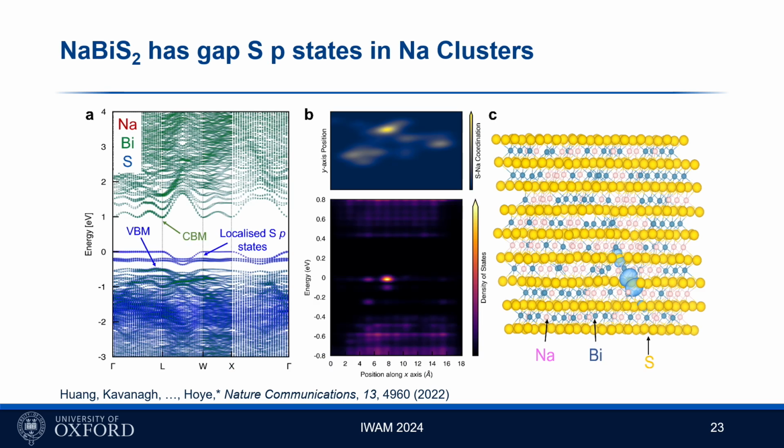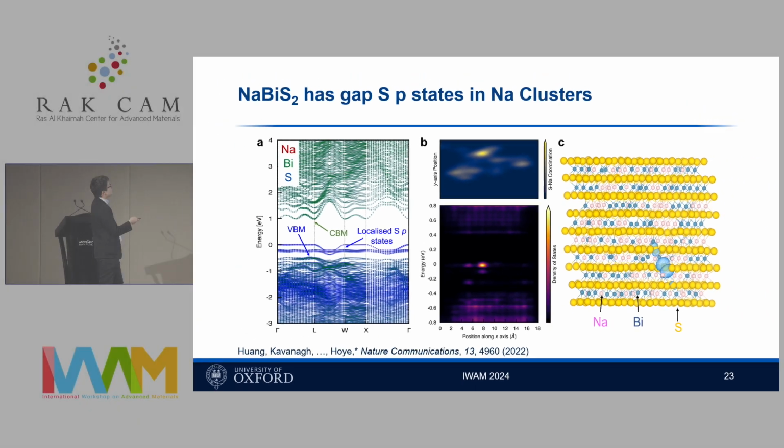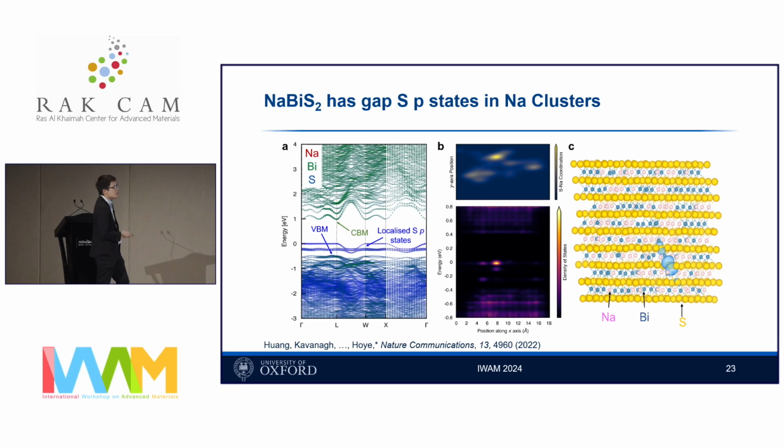But we ought to understand more about the charge carrier transport properties. So here, Sean calculated the energy versus K diagram. And you can see that we have a reasonably dispersed conduction band, a somewhat flatter valence band. But what's quite unusual about this material is that we see these three bands forming within the band gap. And I should mention, in these calculations, there were no defects. So these don't arise due to defects, but they arise due to the intrinsic structure of the material itself.